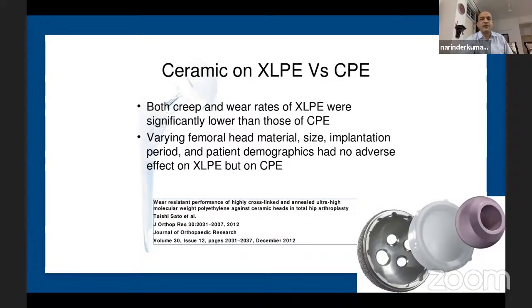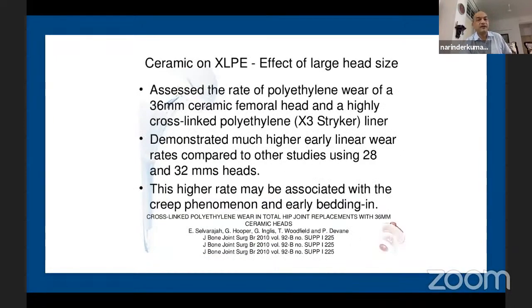Which brings us to ceramic on crosslink poly or ceramic on conventional poly. Most of us are not using conventional poly anymore, because we know that with ceramic on crosslink poly, both the creep and wear rates are significantly better. And this is what most of the studies are also saying. But then the effect of large head size, because this is what most of us try to use. This is showing that 36 mm actually has the accelerated poly wear rate, a higher rate, as compared to 28 and 32 mm. So be careful when you're using large heads with a thin poly liner.